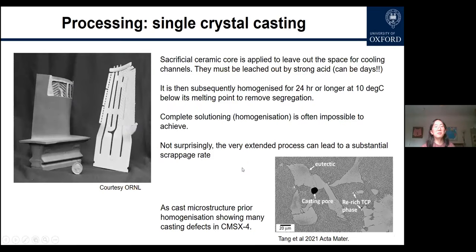Another very important aspect for single crystal casting is what we promised as cooling. To do that, again, this is not very straightforward. You have to have a sacrificial ceramic core. You basically embed these ceramic cores in the wax pattern, and they are cast together with the blade, and they have to be leached out by strong alkali or acid in ultrasonic sound. And that is a very long process.